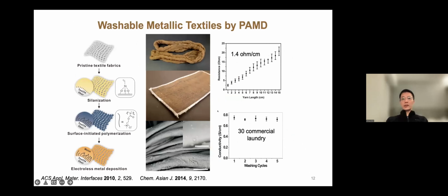Now, these are the metallic textiles of what we made. There's a 300 nanometer thick layer of copper that's deposited on top of commercially available cotton yarns and fabrics. No matter how it's deposited, the surface of each fiber is nicely coated with a layer of metal, and it's dense, conductive, and highly adhesive.